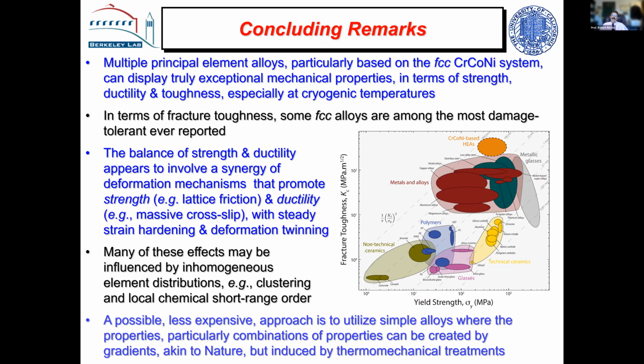Is it possible? Yes, that's interesting, because we've done limited work on looking at how local ordering affects the BCCs, mainly on dislocation mobility. We did a little bit on Peierls barriers, but most of it was done with an MD calculation. And we found that in certain situations it can actually make dislocations move faster rather than slower when you have local ordering.